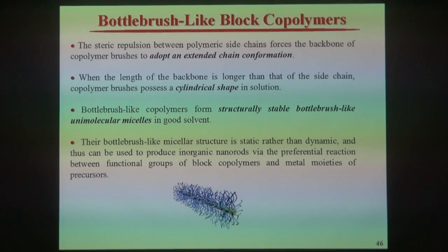What we want to do is to make bottle brush-like copolymers. Here is the motivation: in a bottle brush-like copolymer, all brushes must be connected to the polymer backbone. So they have to adopt an extended polymer chain conformation because of, again, entropic penalty. All polymer chains have to be stretched along the backbone, perpendicular to the polymer backbone. Eventually, they adopt a cylindrical conformation. They also form these unimolecular micelle-like structures, just like this cartoon shows.